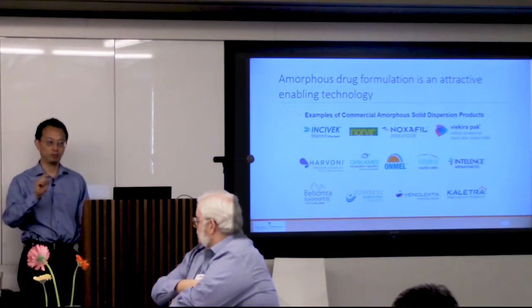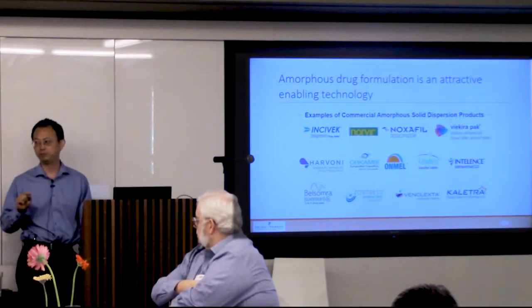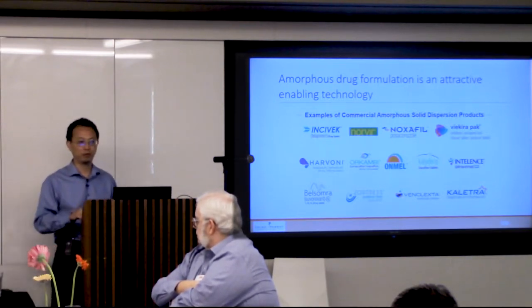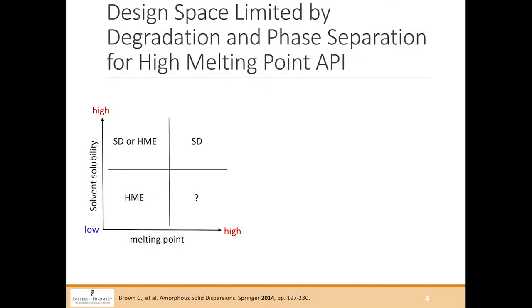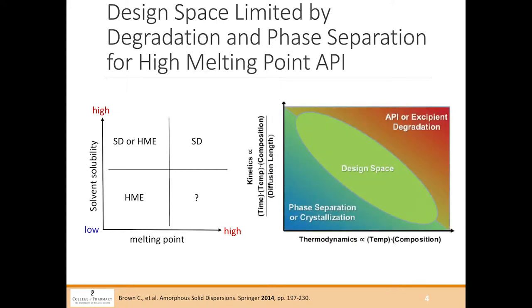The failure is because the drug is not stable, or has different PK performance. So if the drug's melting point is really high, you may have to go to spray drying. Or if the drug is not soluble in organic solvent, you may be stuck with extrusion. However, to make amorphous solid dispersions during the extrusion process, there are several factors involved.